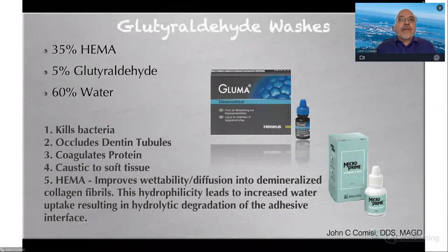Glutaraldehyde washes have really been used a lot as well. If you look at the composition of these materials, it's 35% HEMA, 5% glutaraldehyde, and 60% water. Now, we were just talking about water being part of the problem, especially with the enzymatic breakdown that occurs. And yes, it will kill bacteria on contact, and it will help occlude the dentinal tubules, coagulating the proteins, but unfortunately, it's very caustic to the soft tissue. The HEMA also improves the wettability and diffusion of the demineralized collagen materials, but its hydrophilicity leads to increased water uptake over time. So even our glutaraldehyde washes are problematic.